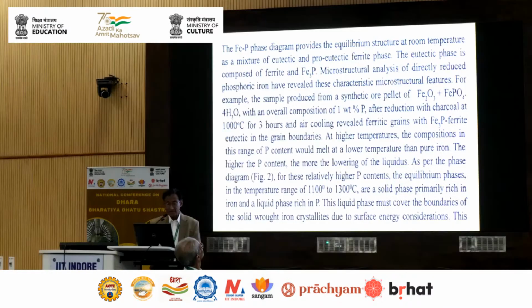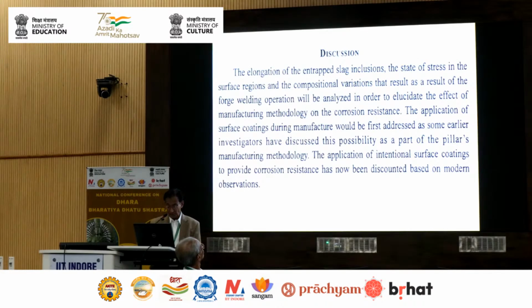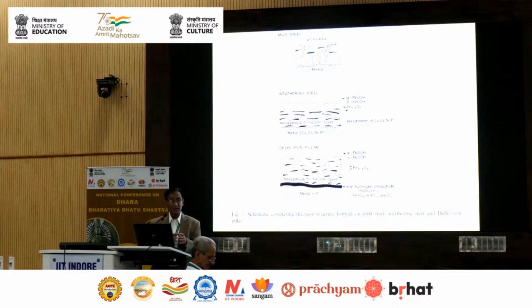But the point is that if you put copper and phosphorus, the corrosion resistance in normal steels also improves. So we call them the corrosion resistant steels in the modern times, in the 40s. This is, of course, Balasubramaniam's work. According to him, the iron hydrogen phosphate hydrate and the amorphous delta FeOOH layer is what actually contributed to the corrosion resistance.